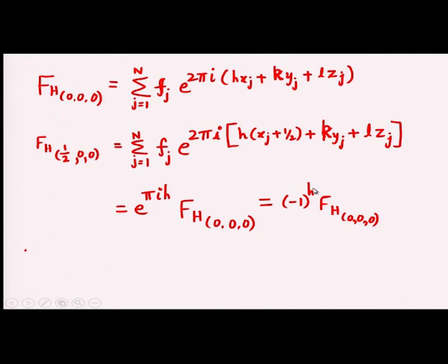So, what I am telling you is that whenever this origin is shifted from the parent origin 0 0 0 to some other origin, we have a phase factor coming out. Now, we have 8 types of origin, and the reflections h k l have 8 parities. For example, odd, odd, odd, or even, even, even, odd, even, even, even, odd, odd, like that 8 parities are there.